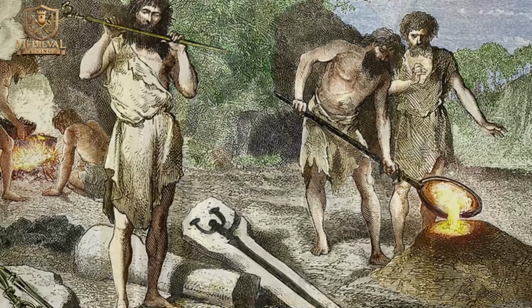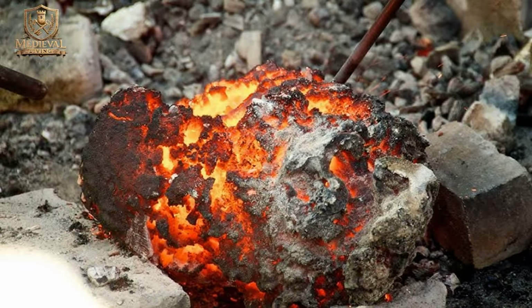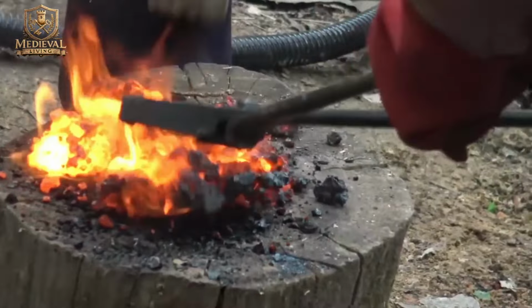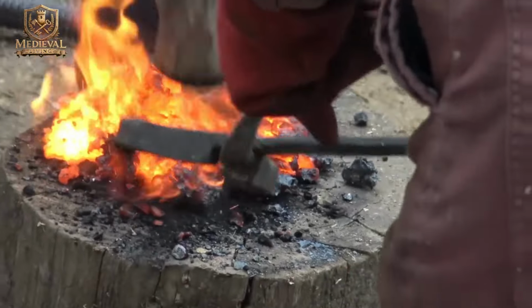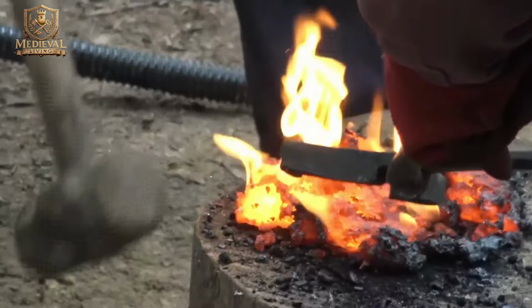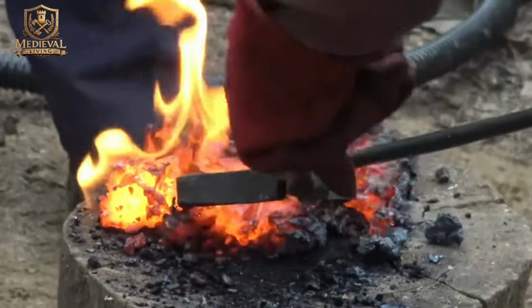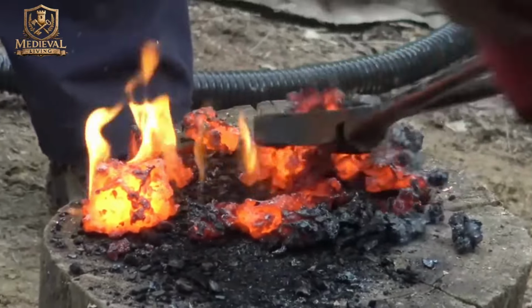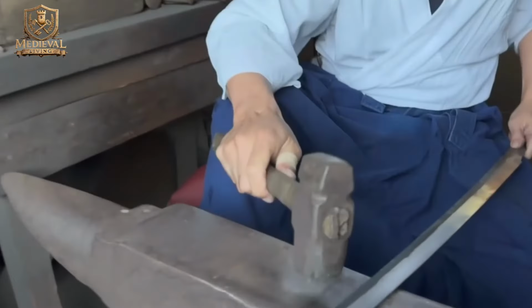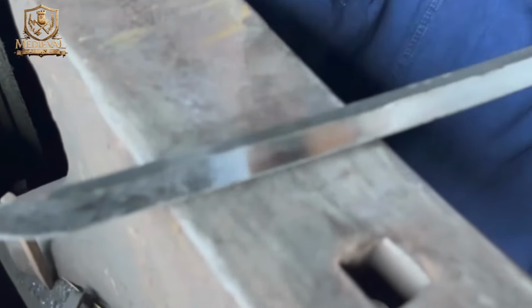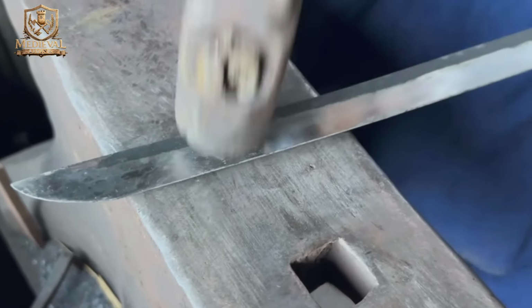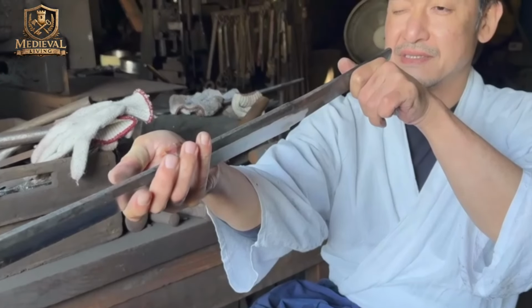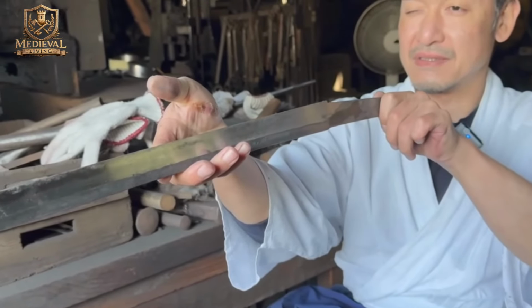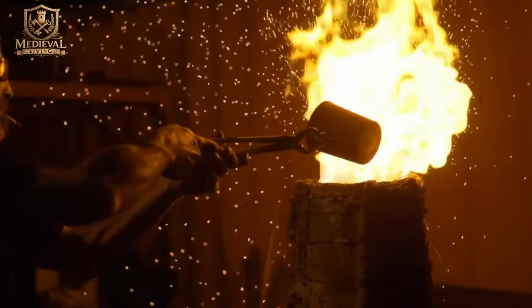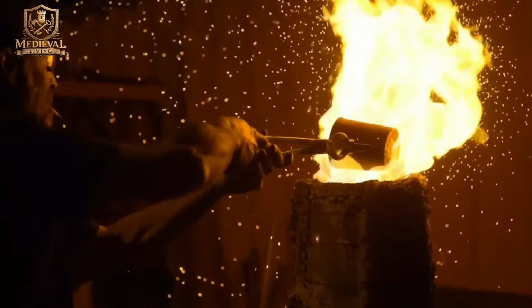The bloomery also enabled composite construction. The bloom contained iron with varying carbon levels. Skilled smiths identified these differences by spark patterns and behavior under the hammer. Higher carbon pieces were reserved for cutting edges. Lower carbon wrought iron formed the body. Forge welding combined them into a single tool. Hard where sharpness mattered. Tough where impact occurred. Pattern welding added additional interfaces. These interfaces increased internal boundaries where slag fibers accumulated, further interrupting corrosion pathways. The blade functioned as a system rather than a single compromised material.